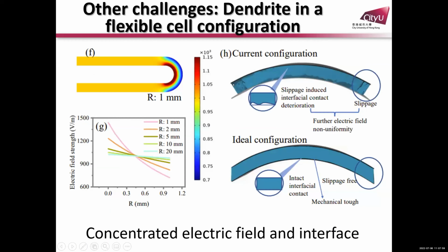We tried to analyze this. There are two issues for the flexible configuration. One is that if you fold it, if you bend it, for example, you have a highly concentrated current density, a concentrated electric field here, that will induce non-uniform growth of the dendrites. So this one, physically, we cannot solve. But on the other hand, there's another issue: when you bend it and you use, for example, a hydrogel electrolyte, you have detachment between the